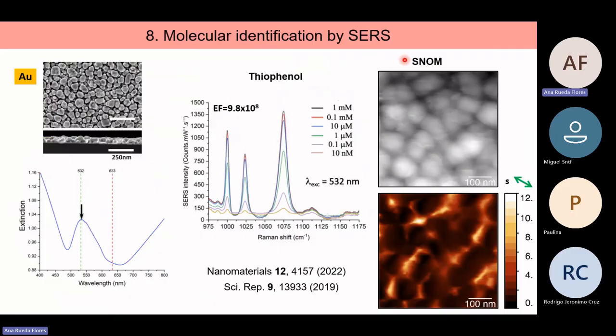Again, using scanning near field optical microscopy, we can see the topography, and at the same time detect the optical signal. You can see that in the interspace between neighboring columns, for instance, this space between these 4 columns, is a region where the light is concentrated, or here, for instance, or here. So we have what we call hotspots, regions where the light is concentrated. When we put a droplet of the solution on top of this template, the molecules that fall on top of one of these hotspots are going to have the Raman signal amplified. And that's why we achieve such a good detection.